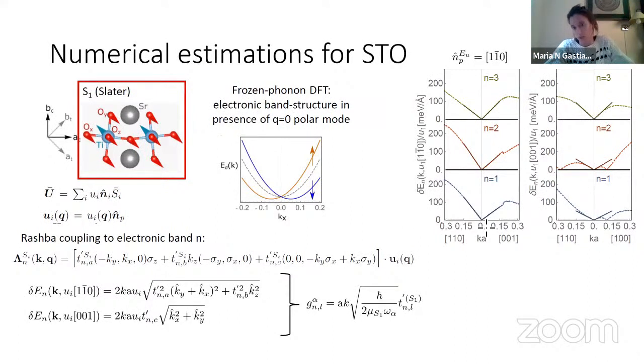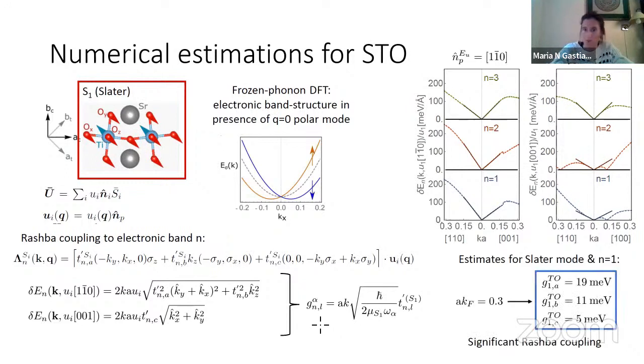So these are the examples you get for bands 1, 2, and 3 for a particular mode, which in this case is in plane. And you see this split, which is linear in K, as we were expecting. Then the slope of this is determined by this T prime along different directions, and by fitting those slopes that you get from Ab-initio, we get the G's. And the second take-home message would be the estimates we get for this Slater mode here for the lowest band, for example. Once you do Ab-initio, you get the coupling through all bands and so on. You just want to get three of the estimates